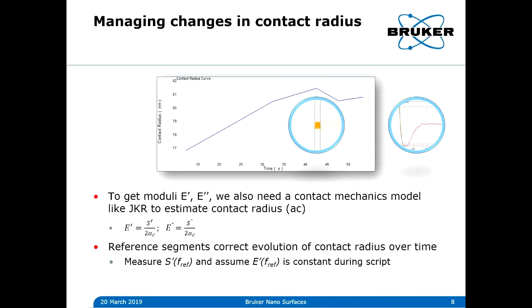We also do a calibration by running the same ramp script on a sapphire sample in order to find if there is any significant phase lag from the electronics or anything else in the system. And usually that'll correct another couple of degrees of phase shift. And that's it, basically. There's no need for a sample at a known modulus, for example. Right, so we do use the hard sample, but we don't need to recalibrate the tip radius. We use the absolute value. Yeah.